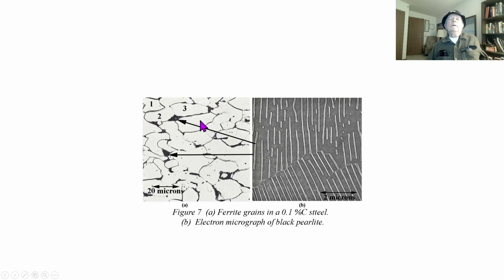This is a slide of a micrograph I got out of a reference. And these little regions called 1, 2, and 3 are individual grains of ferrite, and they etch white in nital. At the grain corners, you often get blobs of pearlite. And you also get it along some of the grain boundaries. If you look at that region of pearlite in an electron microscope, which allows you to magnify it way, way up, you can see what's going on. The white regions are cementite, and the dark regions are the ferrite matrix. These babies are very, very small. This is 2 microns across, so these are less than a tenth of a micron, really small. You cannot see them in an optical microscope at the highest magnification.